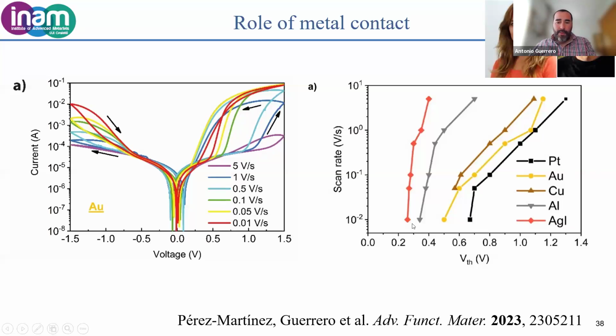for the different metals, and we observe that there is a clear correlation between the reactivity of the metal and this set voltage. For the least reactive metals like platinum or gold, we need to apply high voltages to start to see this increase in current. This is because we need to partially oxidize the platinum and the gold, and this only happens at higher voltages.